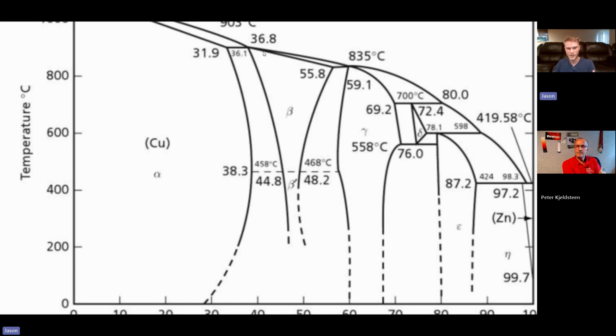And so what's important here is that I want to spend a lot of time in the beta region, because I want relatively large beta grains. If I have small beta grains, the alpha that forms is going to form within a beta grain, right? And if I get preferential growth directions, those growth directions are going to be unique to the crystalline lattice direction of a grain. So from grain to grain, the direction of the alpha is going to change. And I get a better looking structure and also larger alpha if I have larger beta grains. So it's really important to get large beta grains.